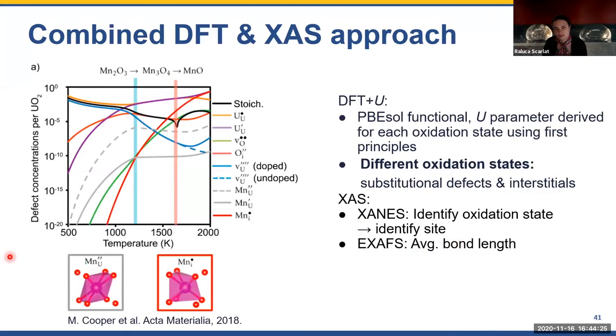What we are trying currently is to dope those materials with manganese. So this is a computational study from Cooper et al. out of Los Alamos. And one of my graduate students is working on a DFT plus U approach of those materials, where he's deriving U parameters for each oxidation state of the manganese as dopant. And we are trying to understand if the manganese is substituting uranium or if it's actually located at an interstitial site, to gain a better understanding of these doped materials, to see if those actually are enhancing the properties of fuel in terms of a slowdown of fission gas diffusion in these enlarged UO2 grain sizes.